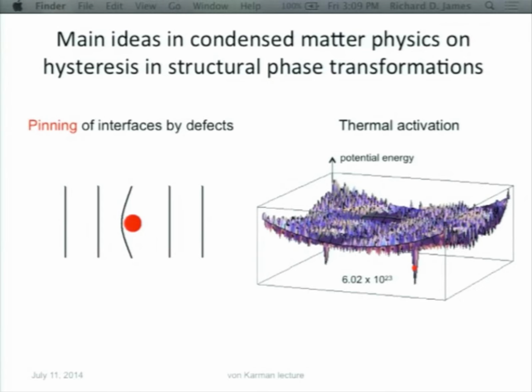A second idea is a very interesting idea and hasn't been completely worked out mathematically, as far as I know. It is the idea of thermal activation. Imagine you could take one of these materials and plot the potential energy surface as a function of all degrees of freedom of the system, parameterized by the positions of all the atoms in the system. It's of course ridiculous, but imagine you could do that. People believe that you would have a very wiggly surface, with some deep wells corresponding to the variants of martensite. Those would be the low-temperature stable phases of the material.